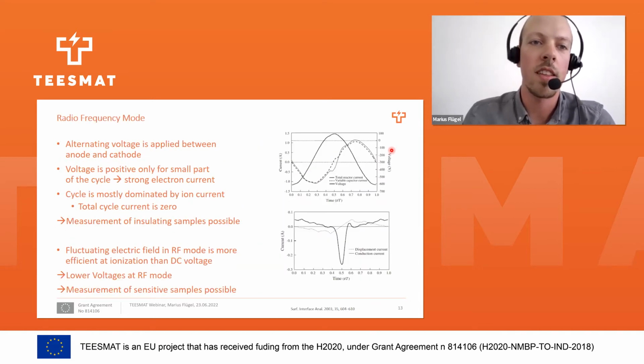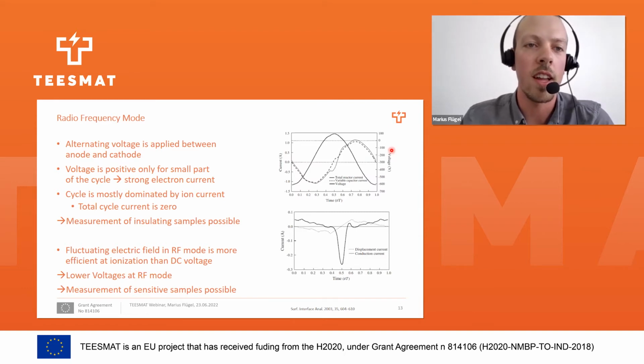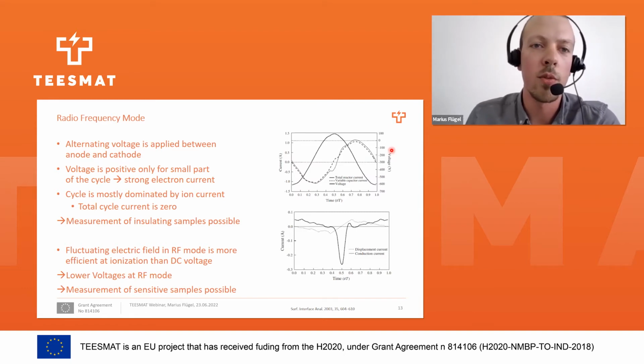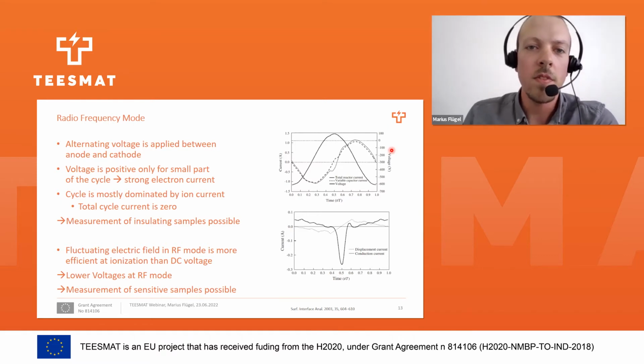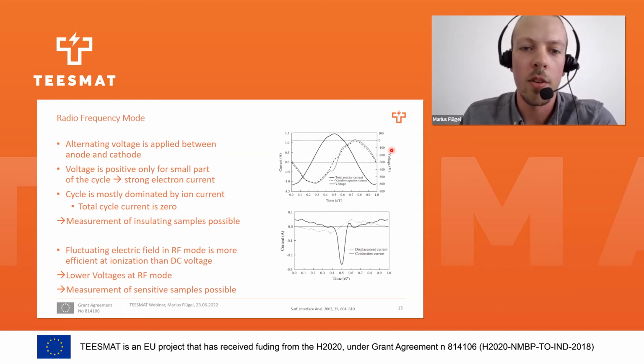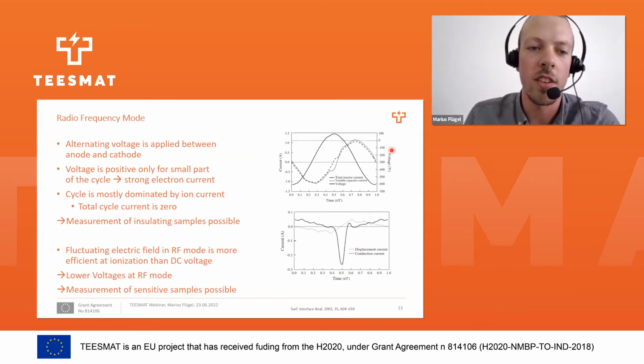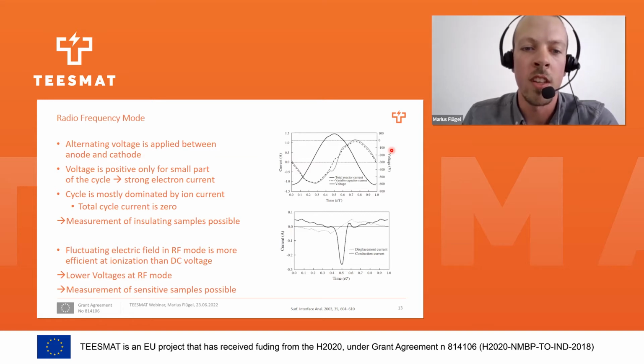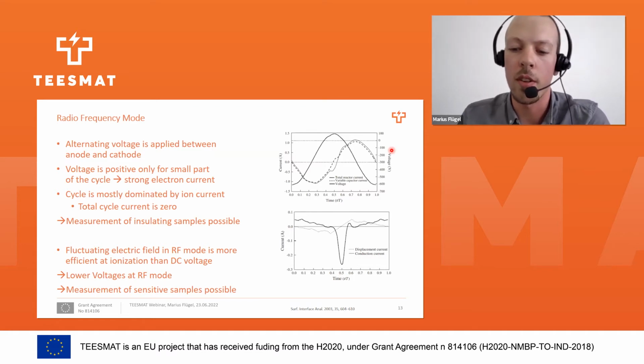For our non-metallic samples, so our graphitic electrodes, we are applying a radio frequency voltage, so that the voltage is positive for a small part of the cycle. This prevents the buildup of a charge on the sample surface. And this RF mode also has the advantage that the ionization is much more efficient than in DC voltage. This allows lower voltages for our RF mode, and sensitive samples, like samples with heavy SEI formation, can also be measured without sample damage.